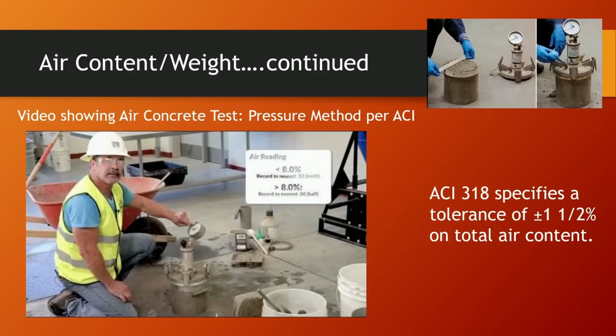After completing the strike off and cleaning of the lip of the air pot, you want to ensure that the seal on the top of the pot is moist. Your third party should have a sponge. They should be using water when they do this. Give it a slight twist to ensure that you don't have any aggregate stuck between the lip and the seal. You're going to lock your clamps down 2 by 2.